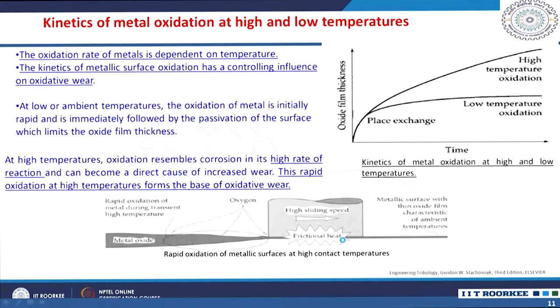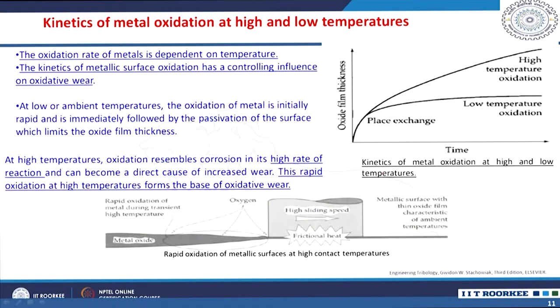So, you will have material removal mainly because of the oxidative wear. As I told, the kinetics of these tribochemical reactions are different, right? So, the kinetics of metal oxidation are dependent on the temperature as well as the stresses. The oxidation rate of metals is dependent on temperature. The kinetics of metallic surface oxidation has a controlling influence on the oxidative wear. If you look at the kinetics of metal oxidation at high and low temperatures, at lower ambient temperature, the oxidation of metal is initially rapid, followed by passivation of the surface, which limits the oxidation film thickness. So, you can see the oxide film versus the time.